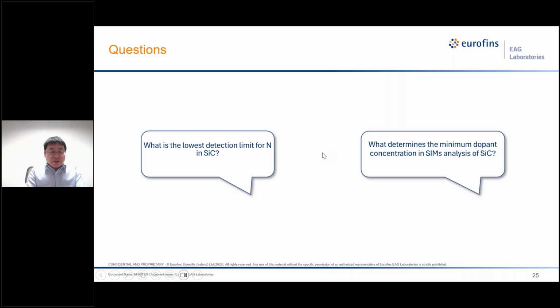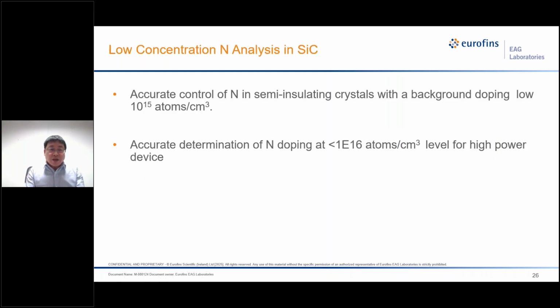So here are the questions related to the detection limit. What's the lowest detection limit for nitrogen in silicon carbide? What determines the minimum dopant concentration in SIMS analysis of silicon carbide? Why is low concentration nitrogen analysis so important? Because for semi-insulating crystal growth, there's always a background doping. At the low E15 level, accurate measurement of the nitrogen in these crystals can provide feedback to the crystal growth. The second reason is for high power devices, the nitrogen doping level is generally lower than E16.